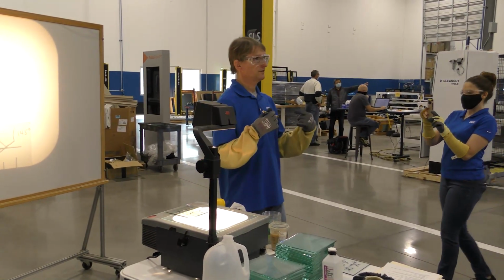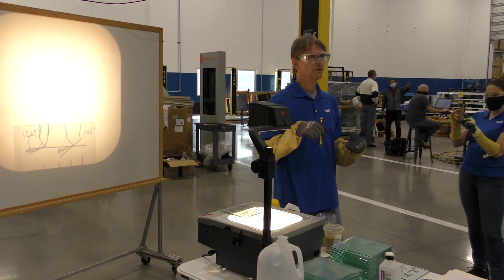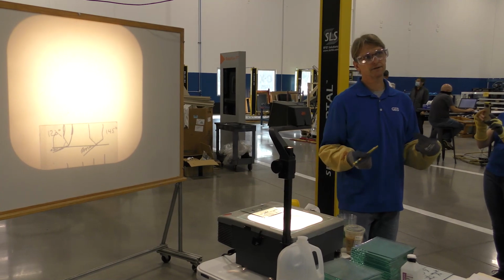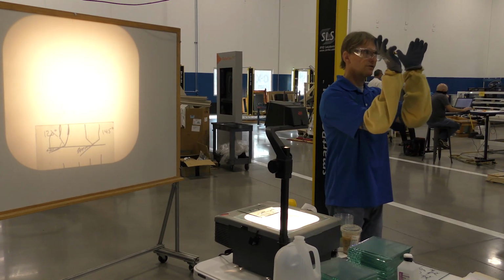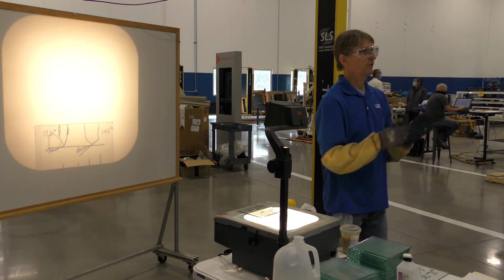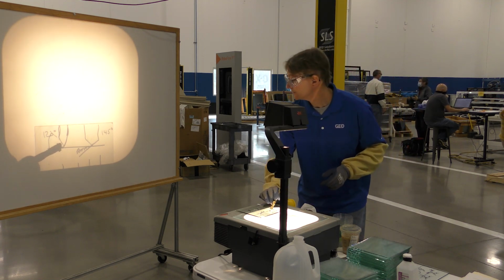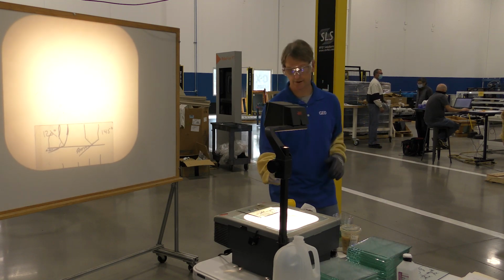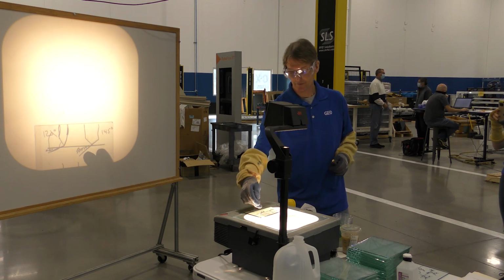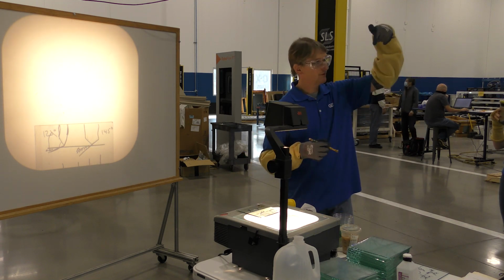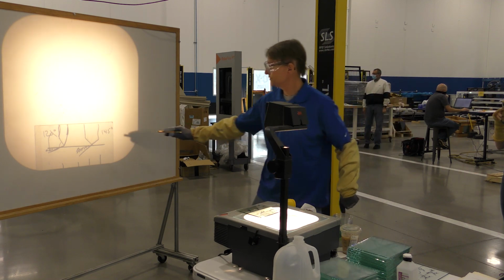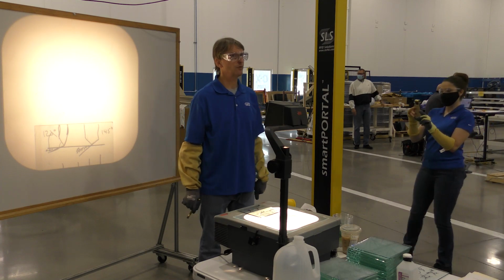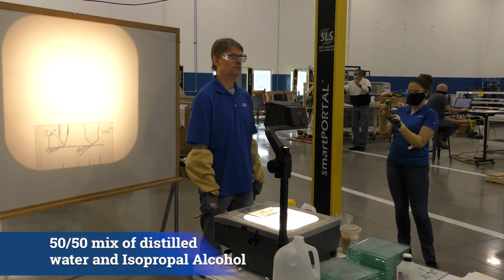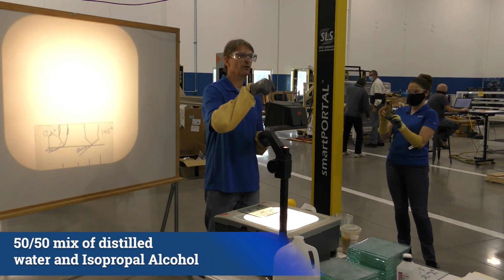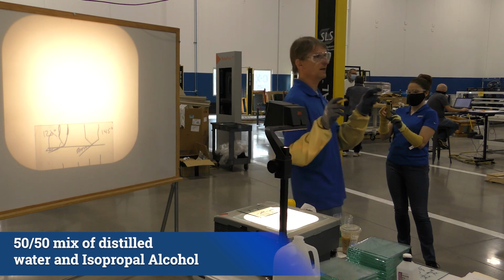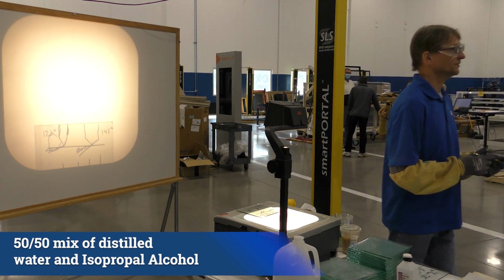The energy that is generated during the scoring process primarily reflects at a 90-degree angle to the angle of the surface of the cutting board. So if I have a sharp angle, here I have demonstrated 120 degrees, it's a little bit exaggerated, versus 145, what happens is the energy and the stress is reflected closer to the surface for a sharper wheel than for a blunt wheel. This is why if you press too hard or if you use too sharp of a wheel, you get what's called a hot cut. And it slivers and it pops and it makes noise.